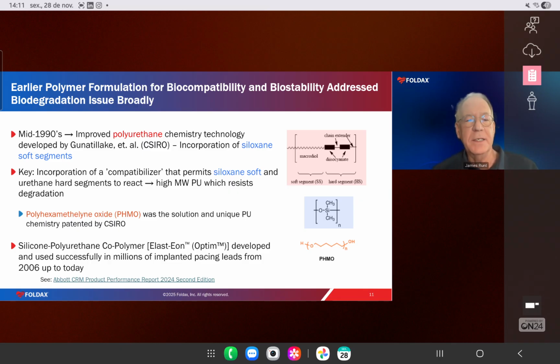In the 1990s, well, let me back up a second. Prior to that, people thought about, can I take silicone rubber, siloxane, and connect it to polyurethane segments and give me a mechanically robust but biocompatible, biostable polymer? But they couldn't find a way to synthesize it. They could make a few thousand molecular weight, but didn't have any mechanical properties that were useful. And the breakthrough was in the mid-1990s at CSIRO, which is a research institution. This site was in Melbourne, Australia.